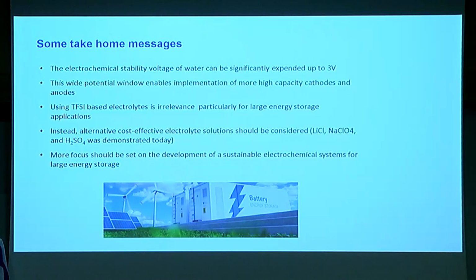So some take-home messages. I showed that the electrochemical stability window of water can be significantly expanded, up to 3 volts. This wide potential window enabled the introduction of new anodes and cathodes. Don't use TFSI if you want to go to practical application. It's good for papers, not practical. And alternative and cost-effective electrolytes should be developed. And this is a general note: more focus should be set on the development of systems for large-scale energy storage.